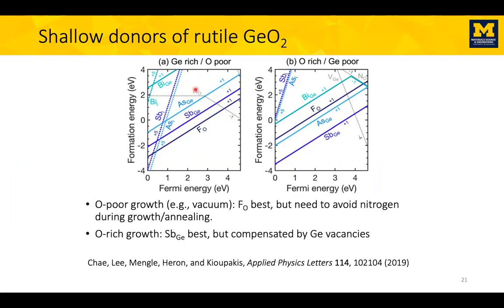However, we need to be careful not to have nitrogen because it competes with fluorine and it would steal its electron. So you don't want to have nitrogen in the growth environment. On the other hand, if you grow under air, let's say under oxygen-rich conditions, antimony is a more candidate donor, but you're also likely to form germanium vacancies and compensate. So probably not the best conditions to achieve N-type doping. So we suggest that oxygen poor conditions or growing under vacuum is more likely to give doping.